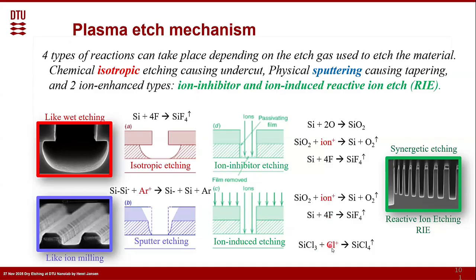However, for silicon, the chlorine atoms, when they have attached to the top side of the silicon lattice, which are freely available, the backbone of your silicon is very difficult to reach by chlorine because they cannot enter. Let's call it the passivation of silicon chloride. Only by impact of ions can it dislodge the bottom side, and then it starts to etch. So it has to wait for the ion before the backbone of the silicon tetrachloride, silicon trichloride in this case, becomes volatile. This is volatile, but you need the ion now. Also, this one is relatively slow.